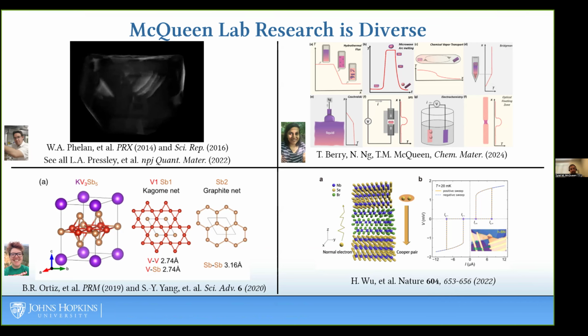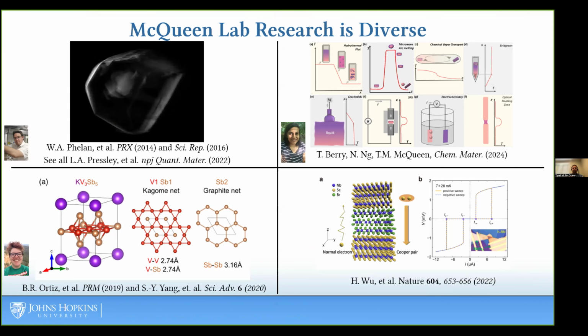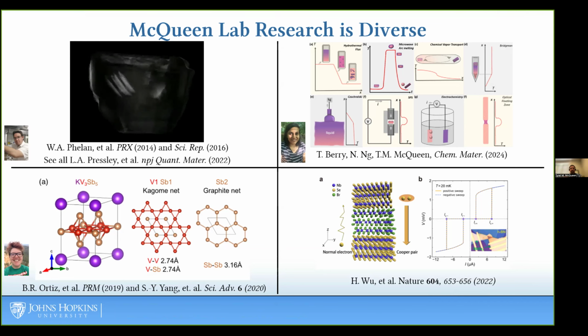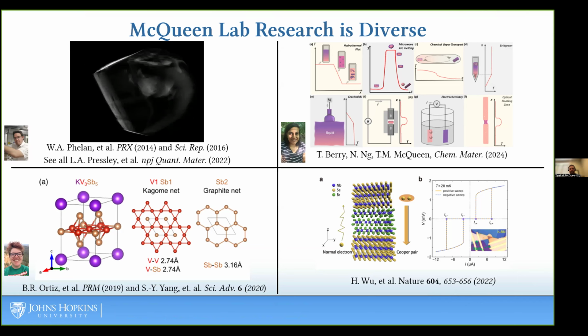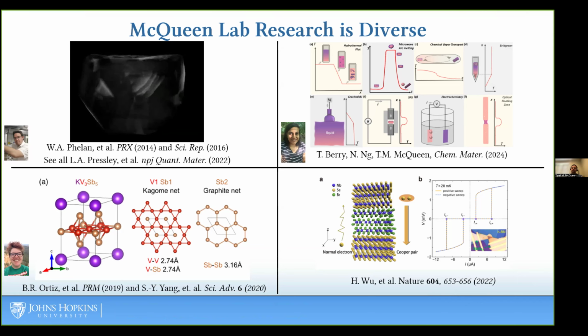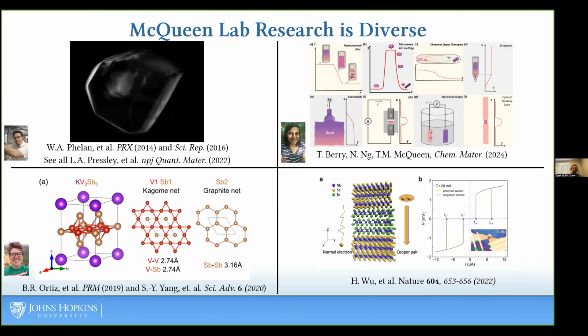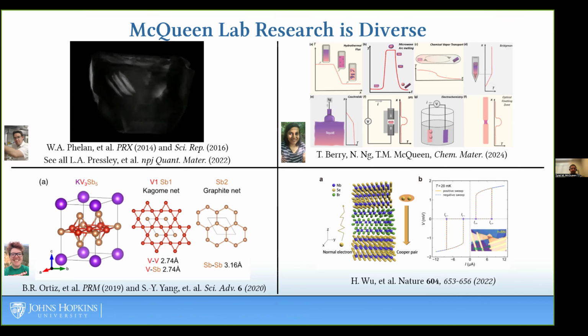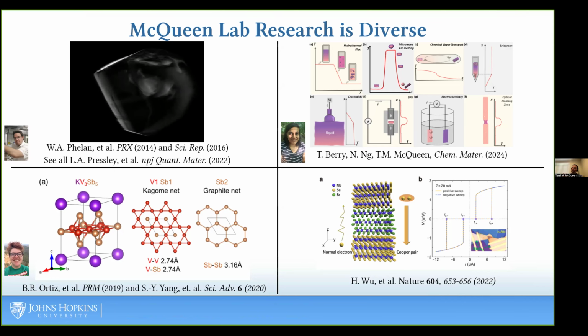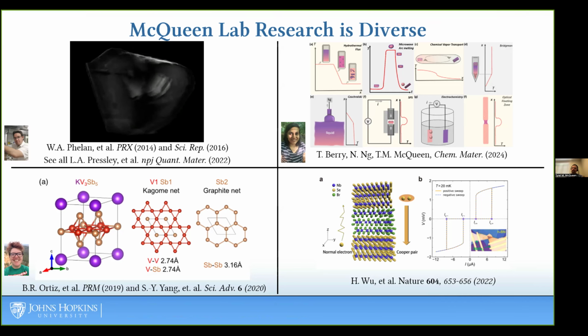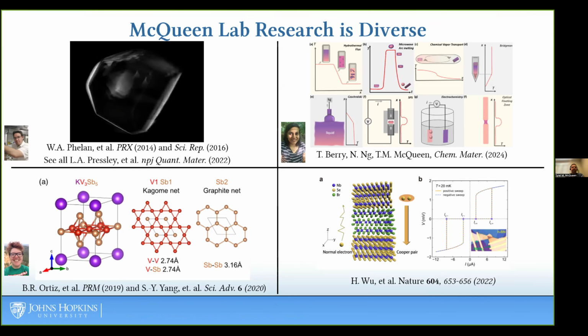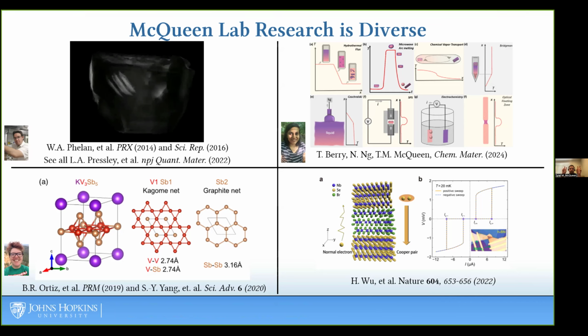And this makes sense because the aluminum and SmB6 have lattice parameters that differ by less than 1%. So epitaxy on each other is totally possible. But the implication of this from a physics interpretation perspective is you cannot, in your analyses, assume that any flux inclusions are randomly distributed in this case, or indeed in many other cases. In fact, oftentimes they orient in very specific crystallographic orientations relative to the underlying lattice, and therefore can still show angle-dependent behaviors, even though you might naively assume that they're randomly distributed.